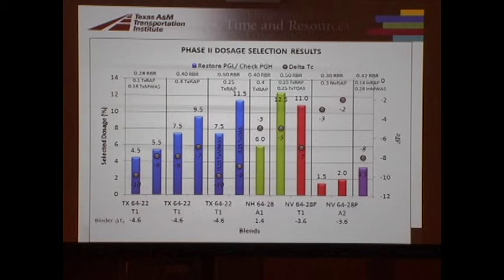But who cares? That's just a matter of how the materials are acting together. But the A1 needs a little bit higher dosage. We definitely see a difference. This is the manufactured waste shingles. This is the tear-off shingles, everything else being the same. So you can see that a higher dosage is needed with tear-off shingles. You can also see the effects of these different base binders. And this final one over here is, it's not labeled, but it's in Indiana: binder, Indiana recycled materials, and a recycling agent that we used in the Indiana field project. So it's just another data point. But all of these are by that first trial approach.